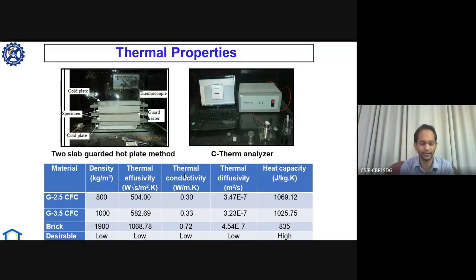Normally brick has a thermal conductivity value ranging from 0.65 to 0.80, and the thermal conductivity of concrete ranges from 2 to 2.5 or 2.75. It depends on the amount of aggregate added and the rock type, whether it is sandstone, marble or granite. In limestone the pores are quite less than in sandstone. If the pores are more, then the thermal conductivity of the aggregate will be less, which will overall impart the thermal conductivity of concrete, because as you know, in concrete typically approximately 60 to 65% is coarse aggregate. So it indirectly imparts the overall thermal conductivity of concrete.